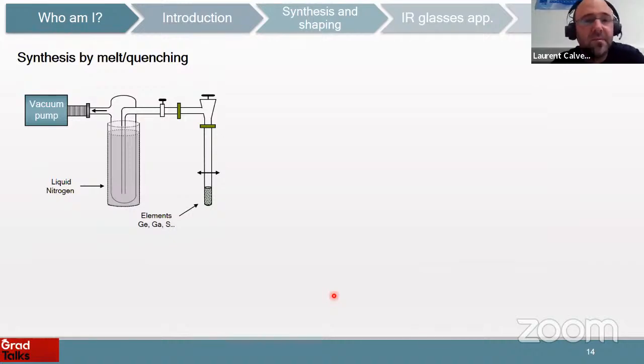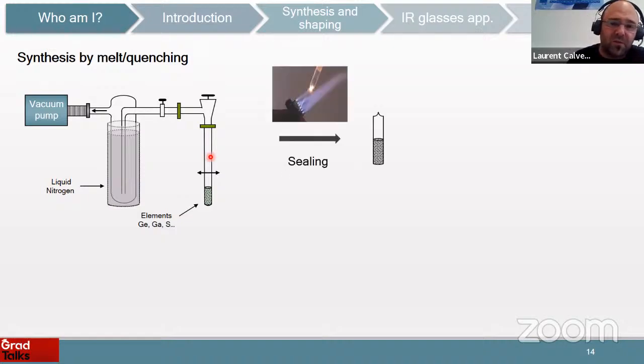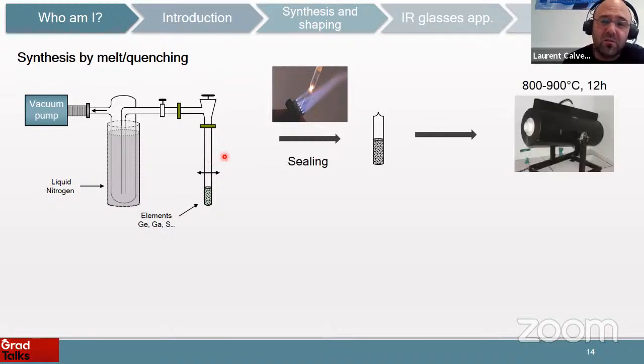How are these glasses made? It's not common. It's not like oxide glasses, where it's pretty easy, because with oxide glasses you can use the melt-quenching method in air. But with selenium and this kind of glasses, you want to avoid oxides because they will absorb the light in the infrared. So you have to do the synthesis in silica tubes that are placed under vacuum to avoid oxygen and water. After one night under vacuum, you can seal the tube and place it in an oven for one night at 900 degrees C. So you will get the liquid inside your tube.